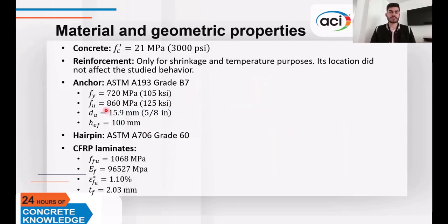These are the material and geometric properties of most of the elements used in this study. We used concrete slabs with a compressive strength of 21 megapascals. The anchors were number 5 ASTM A193 grade B7 threaded rods. Hairpins were constituted by a normal grade 60 bent rebar, and lastly, these were the properties of the CFRP laminates.